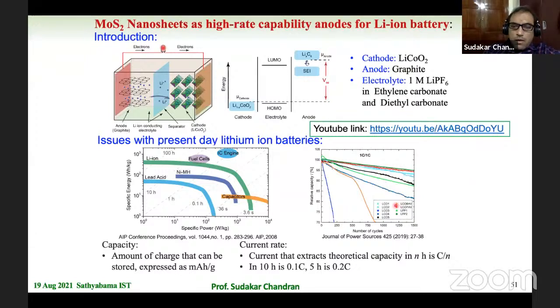Drawing large current basically means, we use a term called current rate. For example, you know the charge capacity of the lithium-ion battery in your mobile phone, you might have come across when you buy a mobile phone that it may be 6,000 milliampere hour, which means that's the capacity, so much charge is stored. And I can draw all this charge either in a minute, or in 1 hour, or in 10 hours, and so on. If I do it in 1 hour, I call this 1 C rate. C by 1 is 1 C rate. If I draw that in 10 hours, C by 10, which is 0.1 C rate.